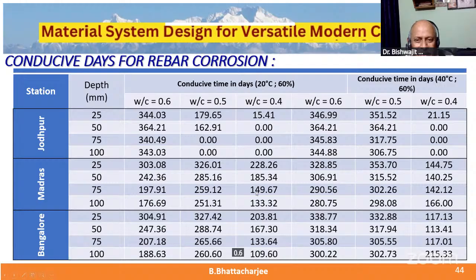The temperature is 40 degrees. Bangalore will not have 40 degrees centigrade temperature unless it's exposed. It will be 20 degrees Celsius. So then you have got this, and this is almost comparable, right? 0.6, 0.4 is somewhere here. So this is the kind of thing. Yes, one can calculate it out. This is a theoretical calculation. The value of the hydraulic diffusivity is to be looked into.